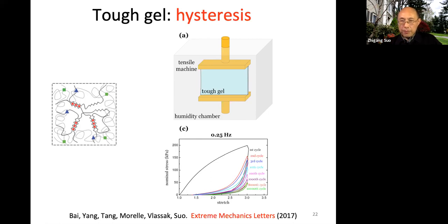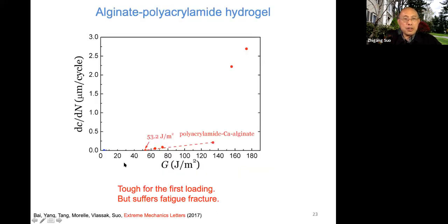Okay. So if we test the fatigue, cyclic fatigue, dc/dN, growth per cycle as a function of energy release rate, indeed, the threshold is 50. As bad as natural rubber. Remember, this material is as good as natural rubber in monotonic loading. So in 2017, 5 years after our Nature paper, we were not too embarrassed to tell the world our material was not very good, but as good as natural rubber. So it's not terrible. Natural rubber is a gold standard for a while, right? Yeah. So that was the status.